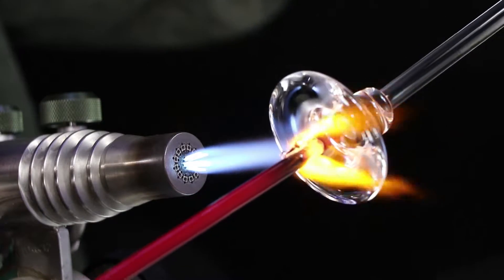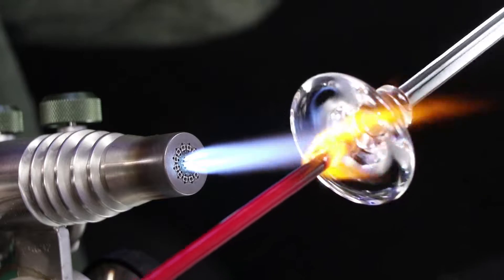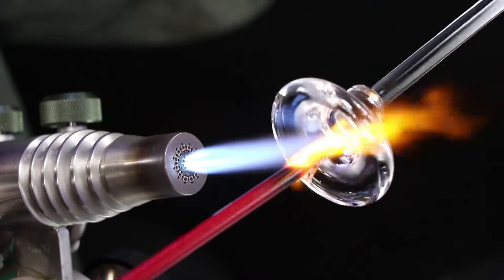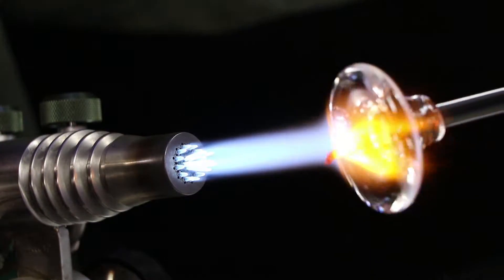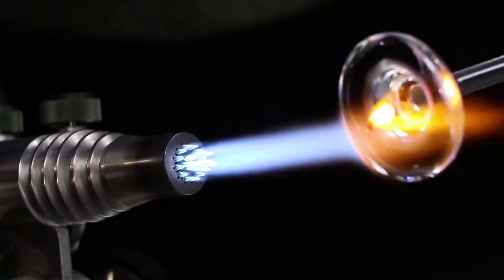For applying dots, you'd most definitely want to warm the glass up that you're applying the dot to. You never want to apply your molten glass to cold glass, as it's going to cause a lot of extra stress and most likely a crack later. It'll also trap a little bit of air between the connection that you can see pretty easily from the inside.